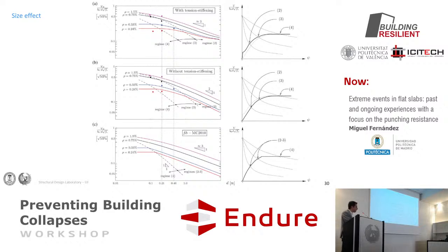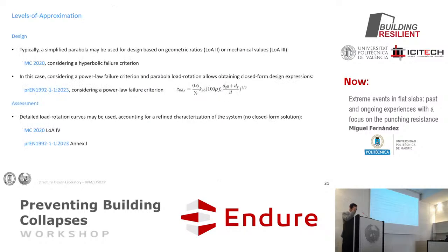Interestingly, when you're getting this relation, which is the linear, when we were saying the bilinear law, and if you are failing within the linear part of the response, you're getting a slope of 1/2. 1/2, as you may typically know, is the slope that linear elastic fracture mechanics gives you. And this is because this is linear elastic. So if you assume a linear elastic response of the member, you will get the slope of linear elastic fracture mechanics. While these slopes, which are milder, are associated with some level of nonlinearity: all these cracks and this plasticity, even regions that are yielding, and tension stiffening effects and so on. So it's a very consistent theory, and I was stating you can use it at different levels.